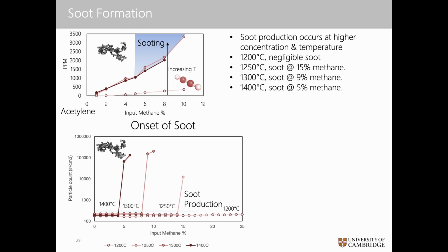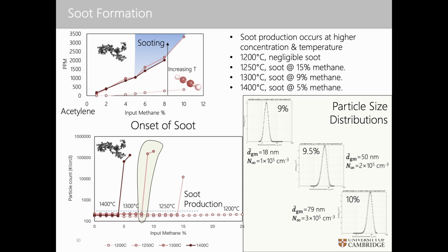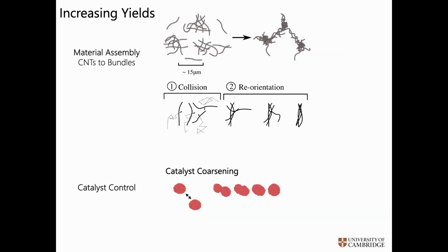So this is kind of like what one does in an automotive emissions test in Europe when we're doing type approval testing: you're measuring particle counts coming out of the reactor, where we're not putting in iron catalyst now. And you just see, when this is logarithmic here, when do you start getting orders of magnitude more particles coming out than initially? And that tells you when you start to get soot production. And then we can do size distributions, and you can look at the amount of mass that is consumed in the unwanted species, soot, relative to the thing that you do want. So that's about what you don't want.